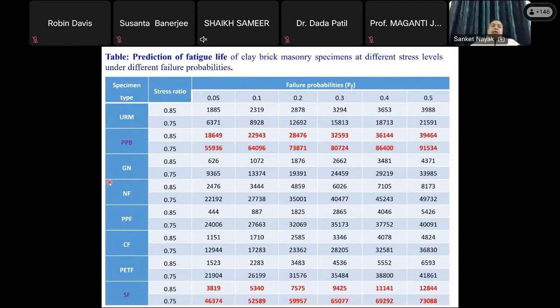Now from this we can predict the fatigue life of the structures. That means at what stress ratio, how many load cycles it can take. The stress ratio is defined with respect to failure probabilities. You can see here also the polypropylene band is performing very well for both the clay brick and fly ash bricks, and steel fiber also performs very good with respect to the other ones. But if we see the plastic fibers, its performance is also not very bad as compared to its unreinforced counterpart.